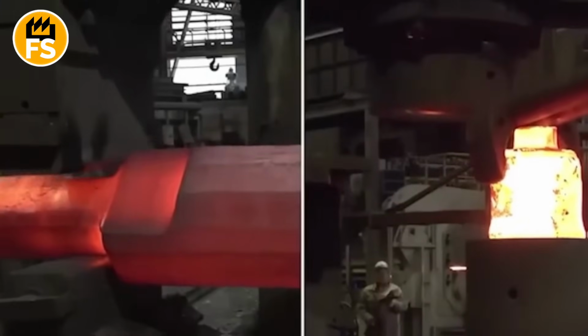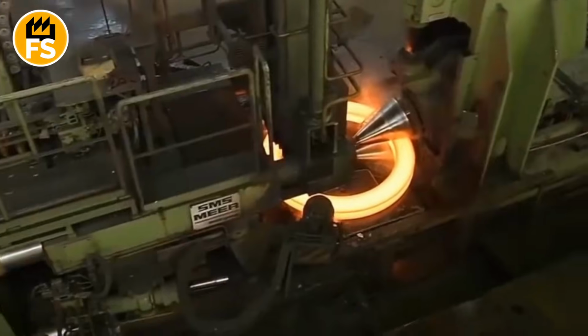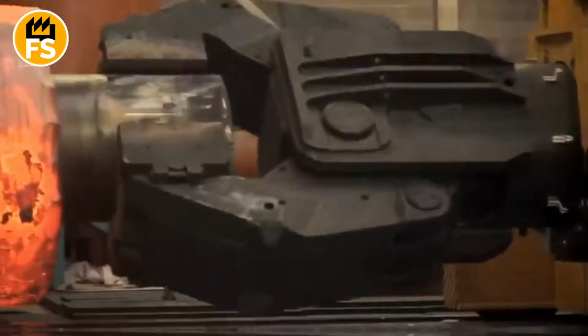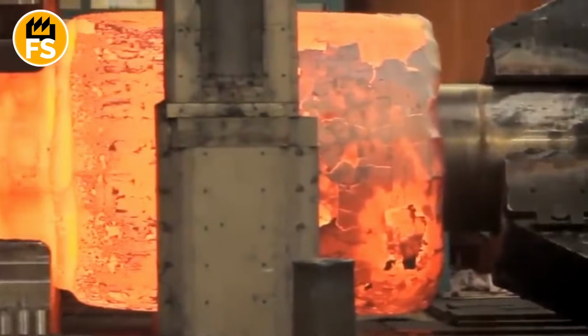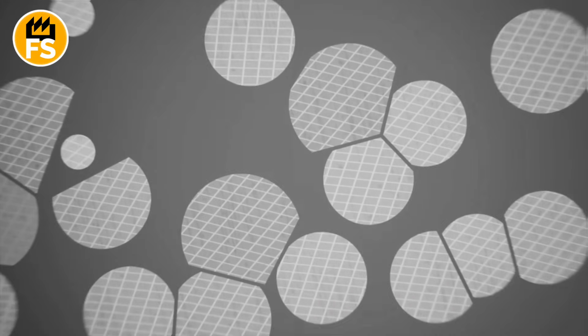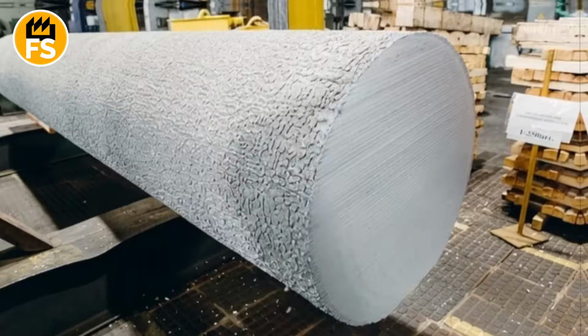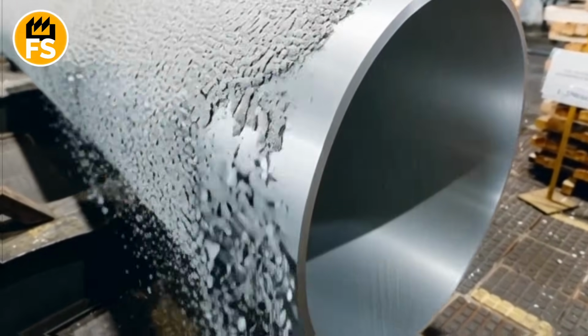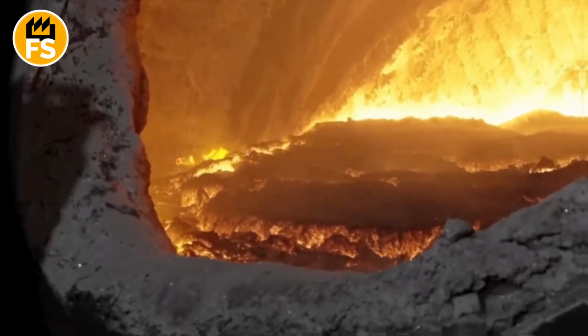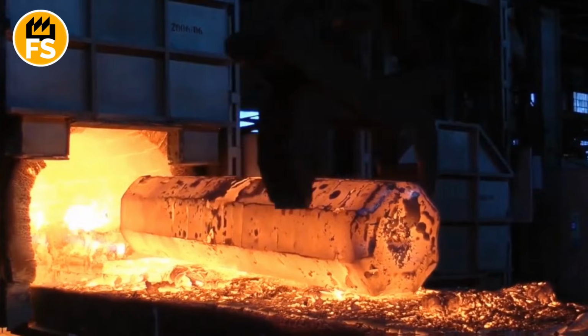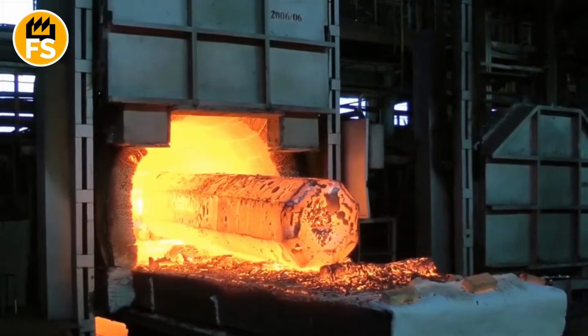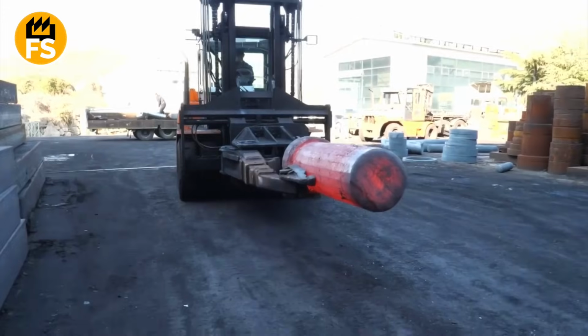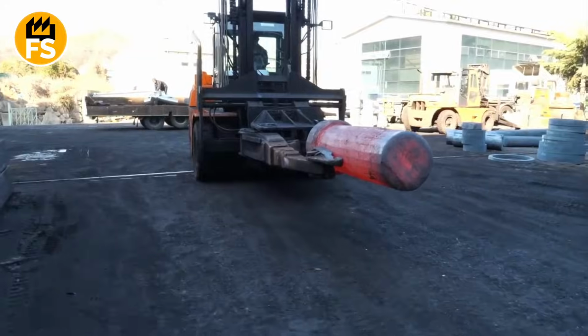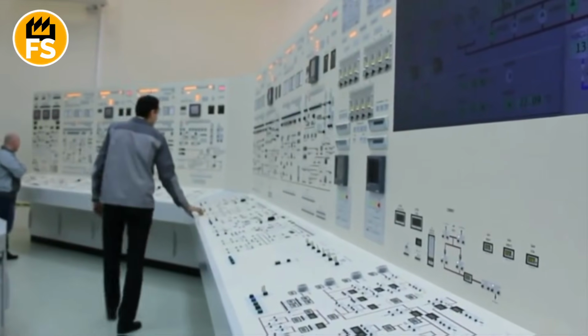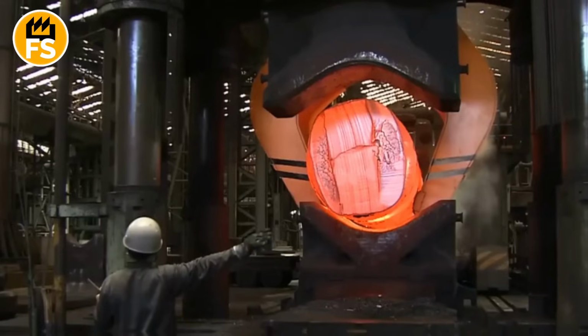You'd think forging is just applying force to metal, but it's actually a much more complex science. When metal deforms under immense pressure, its crystalline structure changes. The steel grains align along the load lines, creating a fibrous structure similar to wood. This directionality makes forged metal far stronger in the direction of the fibers than cast steel. Temperature plays a critical role too. Steel that's too hot can become too soft and lose strength. Too cold, it cracks under the press. Engineers must know exactly what temperature to work with each alloy to achieve optimal properties.